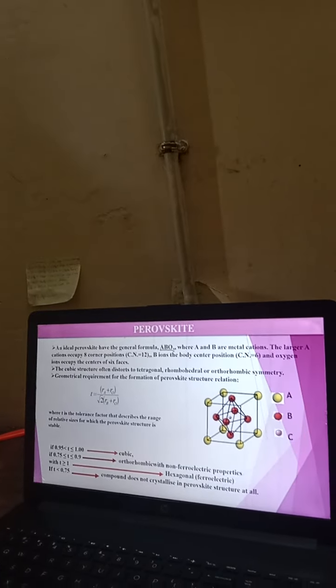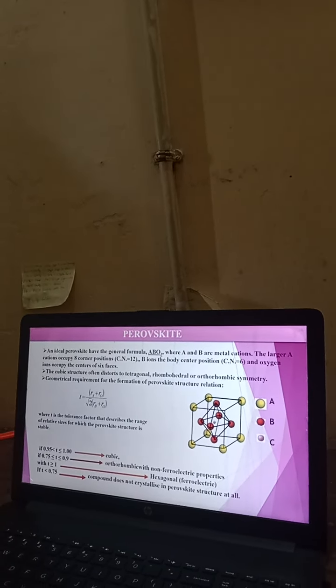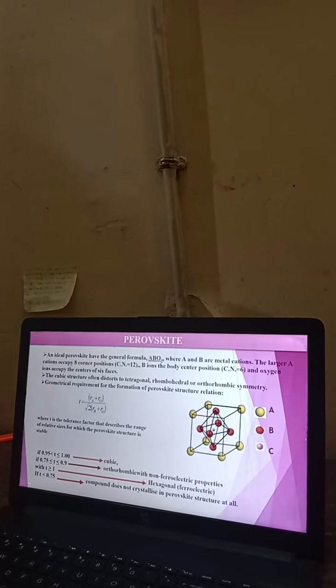If t is between 0.75 to 0.9, then the crystal will be orthorhombic with non-ferroelectric properties. If t is greater than or equal to 1, then it will be hexagonal. If t is less than 0.75, then the compound doesn't crystallize in perovskite structure at all.